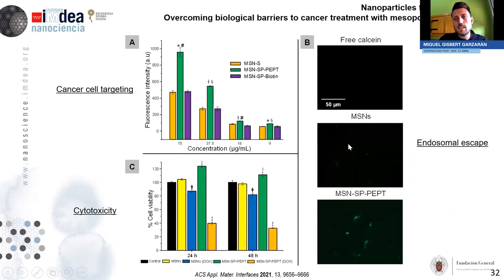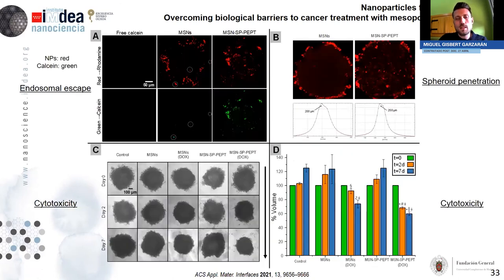So after that, this is a two-dimensional cell experiment. So we moved to three-dimensional cell experiments. So we grow A549 cancer cell spheroids, and we carried out the same experiments. And as we can see here, it is clear that only in the case where we had the complete system, we were able to see the fluorescence from calcein. So we checked again the endosomal escape capabilities of the system. Also, this is quite interesting because we observed improved penetration towards inner areas of the spheroid in the case where we had the complete system.